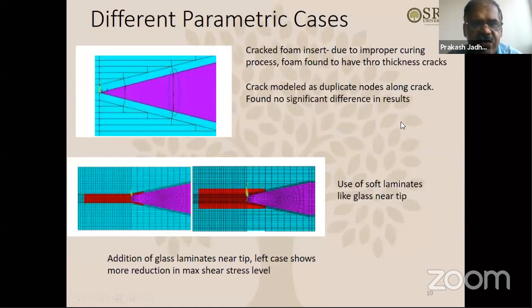Then going ahead, there were some more cases we tried. What we found here is when you use the polymeric foam, and suppose the curing did not happen properly, some cracks were already in the coupon, in the polymeric foam part, vertical cracks like this. So how do you model that vertical crack? In case the curing is not proper, then these cracks will be existing there. We tried to model those cracks using duplicate nodes, and we saw that it doesn't have a significant impact on the interlaminar shear stress level at the tip.